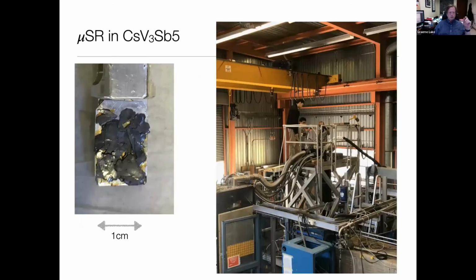Okay. So we've done a series of measurements now on cesium vanadium 3 antimony 5. Here's a picture of our sample holder that's about 1 centimeter wide, and here you see a series of crystals that have been glued to the silver sample holder. So this whole square centimeter of sample is loaded on top of a dilution refrigerator by a bunch of graduate students and scientists up here. Actually, this was an undergraduate at the time.